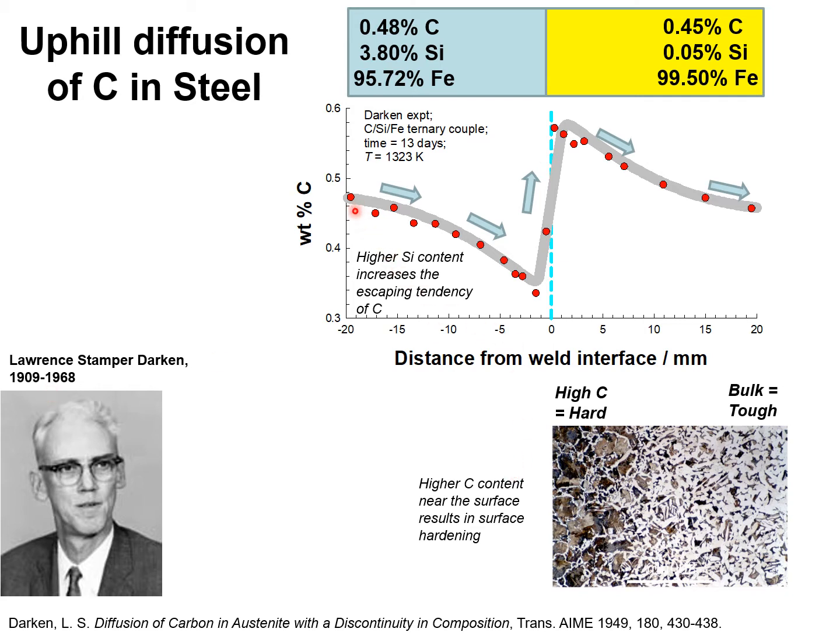We note that there is a decline in the weight percent of carbon as the interface is approached from the left bar, and then the weight percent of carbon increases to reach a maximum in the right-hand compartment, and then finally decreases in value to the initial value of 0.45%.